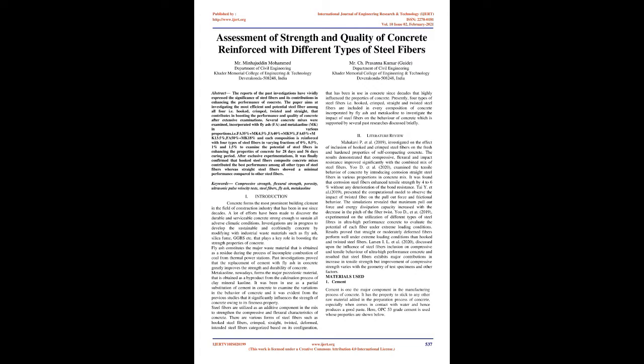After extensive experimentations, it was finally confirmed that hooked steel fibers composite concrete mixes contributed the best performance among all other types of steel fibers, whereas straight steel fibers showed a minimal performance compared to other steel fibers. Keywords: compressive strength, flexural strength, porosity, ultrasonic pulse velocity tests, steel fibers, fly ash, metakaolin.